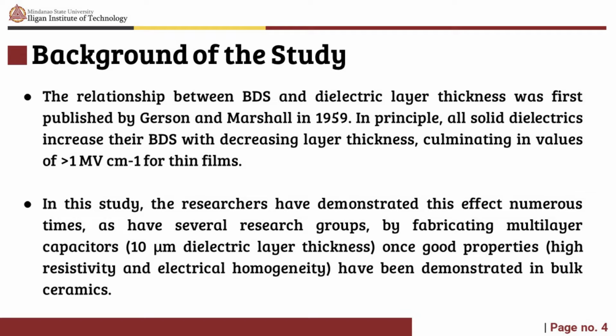This is done once good properties, high resistivity, and electrical homogeneity have been demonstrated in bulk ceramics. However, with any given multi-layer, short-circuit pathways can emerge between low resistivity regions as layer thickness decreases, thereby decreasing BDS. The caveat, therefore, which must be applied to the Gerson and Marshall relationship is that BDS will only increase if low resistivity pathways are eliminated, in that the materials have a high resistivity and are electrically homogeneous.